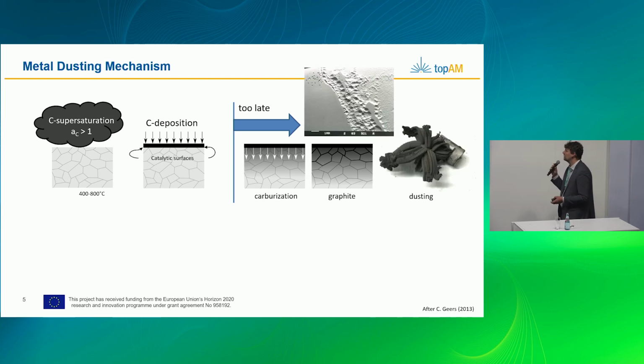It also carries a high risk. What you form are pits, and this is a picture from our lab on the right, where the alumina crucible that you can see in the back could not hold the sample anymore because of all the graphite produced there. It's completely crushed, and the sample is in the middle of what looks like the center of those graphite strings.